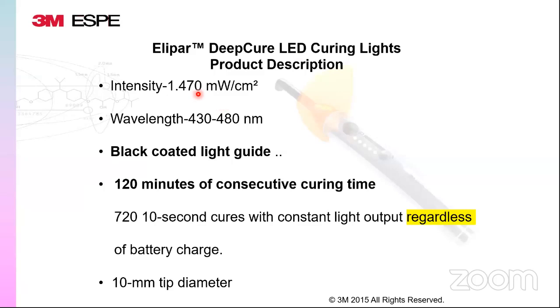So by the time it reaches the 6 mm depth, it goes to approximately 1250 milliwatt, which is good enough for my base level. Wavelength is 430 to 480, back coated, which prevents any scatter of light. 120 minutes of consecutive light curing.